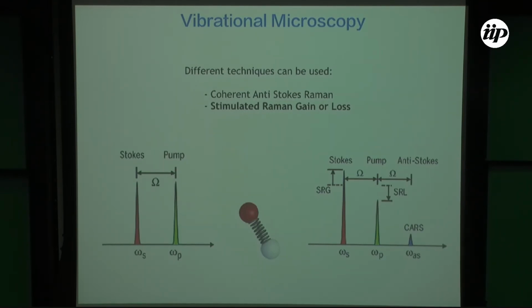There are some problems of doing that with microscopy. I'm not going to go into details. Mainly because with CARS, as I told you, the chi-three always has the resonant part and the non-resonant part, okay? So sometimes, depending on the type of samples that you have, for example in graphene, okay, the electronic contribution was so large that the phonon part was very small, okay? So doing CARS microscopy on graphene would not be ideal, okay? But we can do something different.